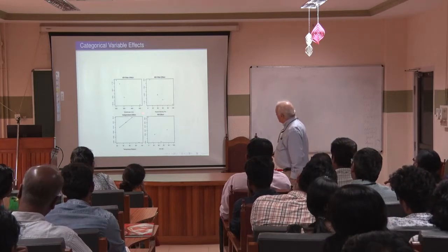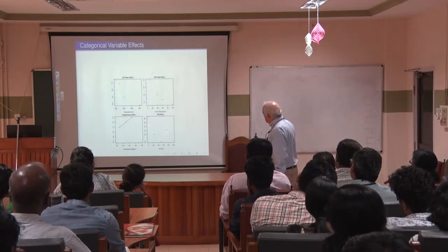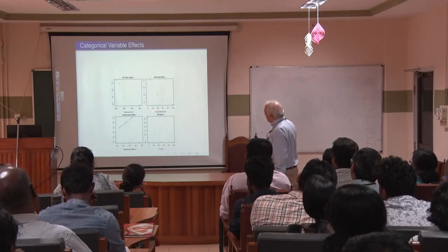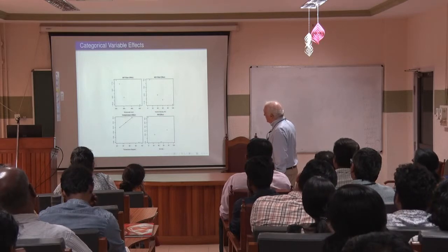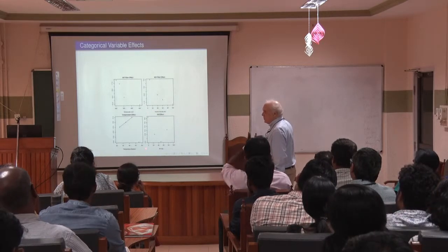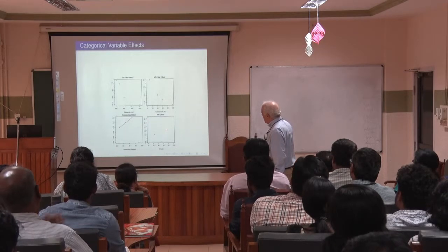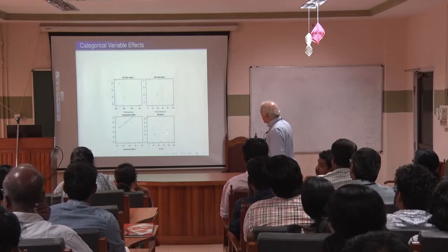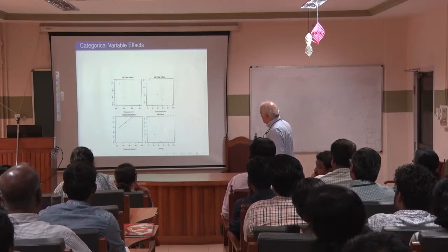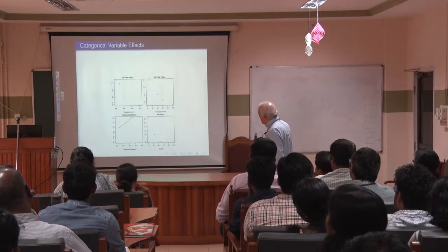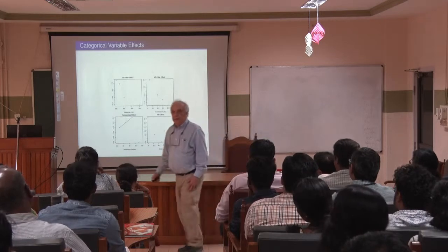And then this was the surprise here. The relative humidity effect tended to be high at low humidity. We call this the dry condition. And also tend to be high at the higher humidities and low in between. This is a surprise to the scientists.